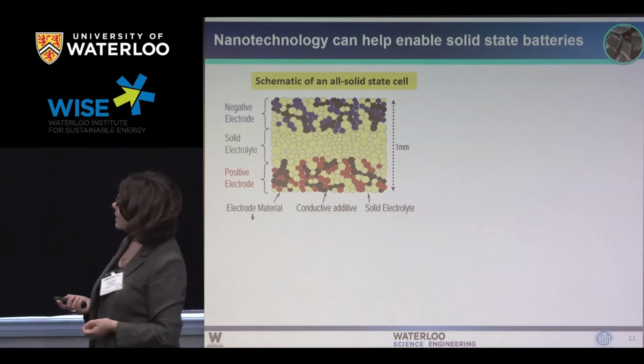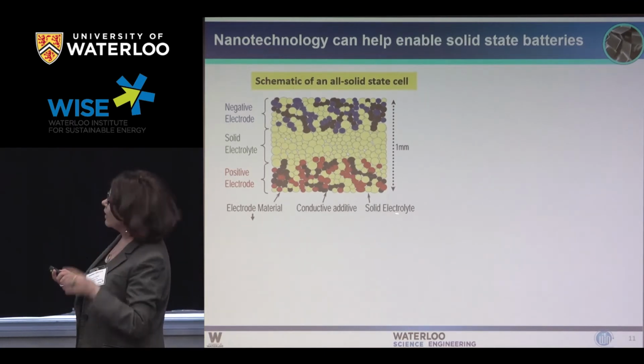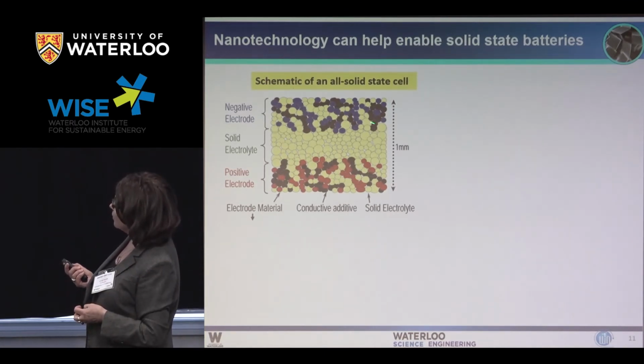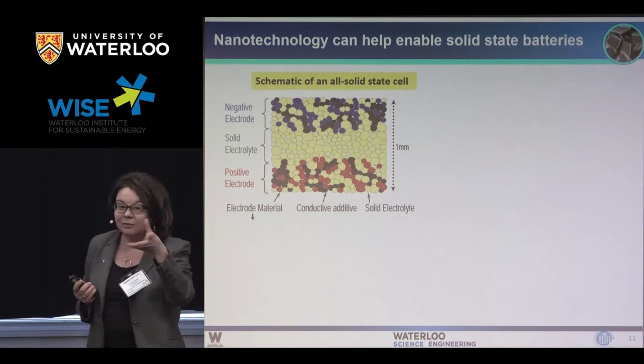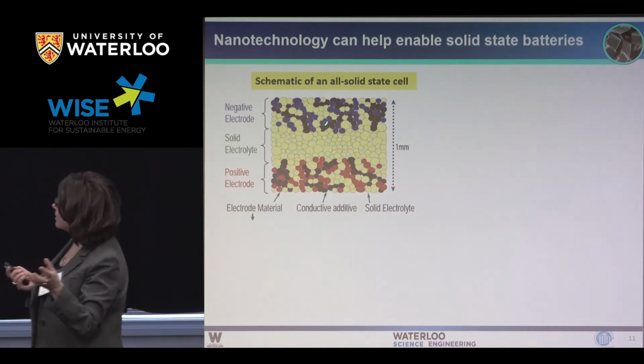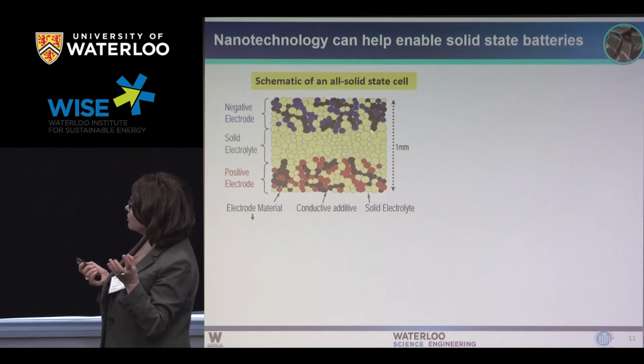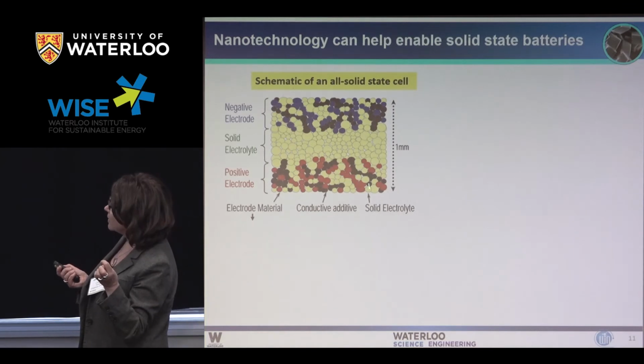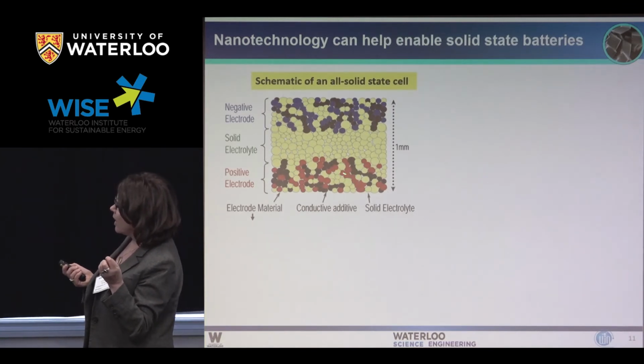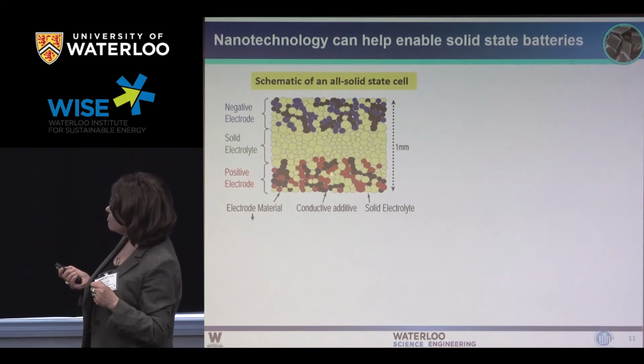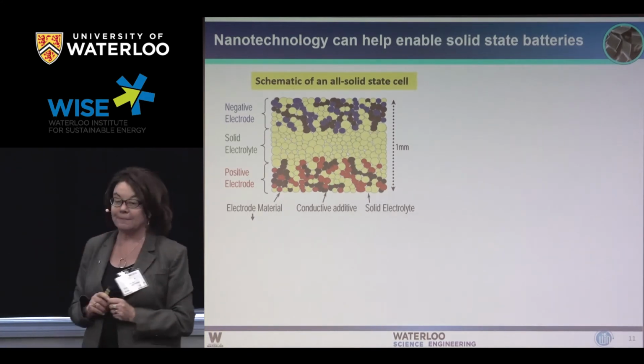So what is a solid-state cell? Well, it's sort of like the one that I showed you, except that you have a negative electrode, and the electrolyte is this solid, this yellow stuff. So at the negative electrode, you have the active material that transfers electrons, that's the blue stuff, and it's mixed with the yellow particles and some carbon additive. And at the positive electrode, you have your positive electrode material, which is the red, that's at high potential, again, mixed with the electrolyte and some carbon.